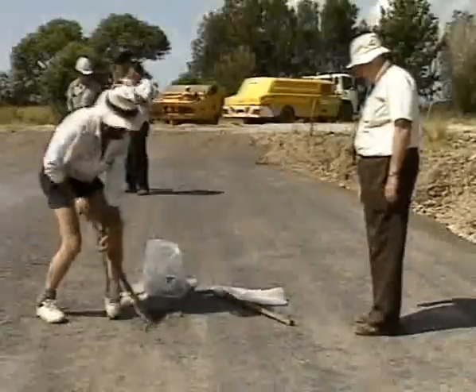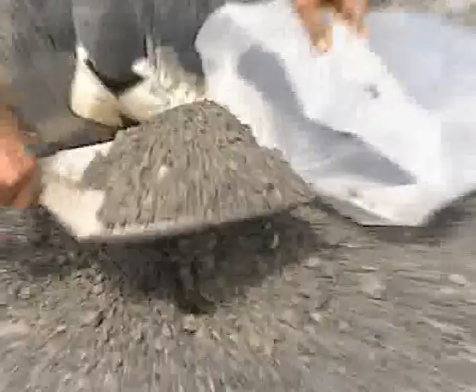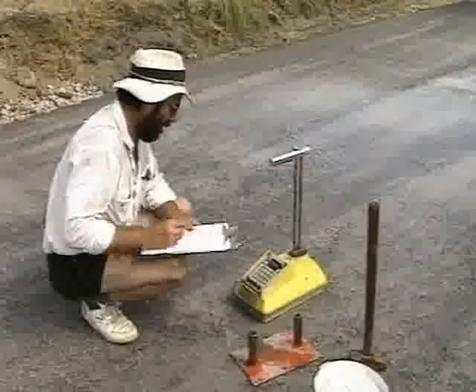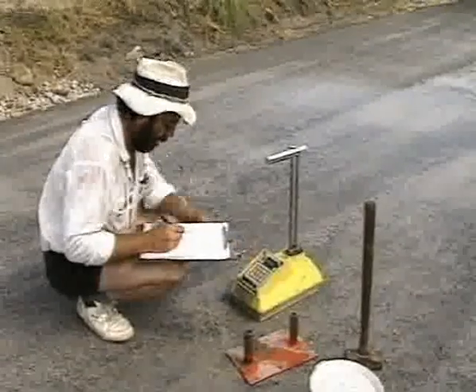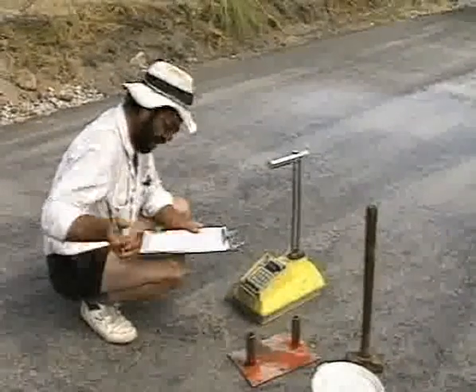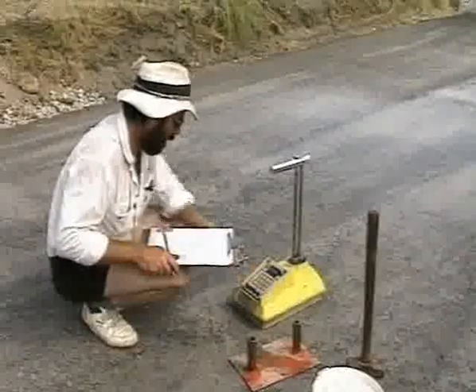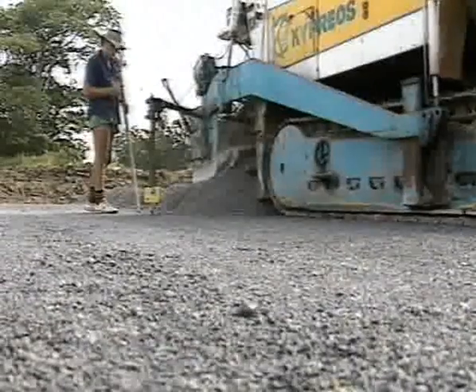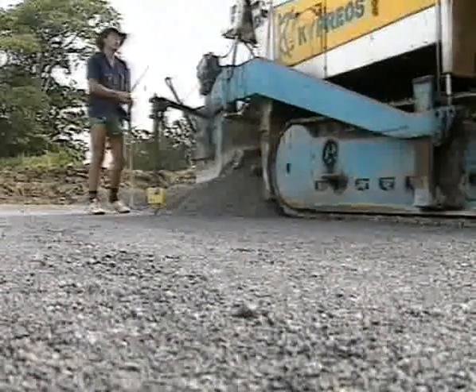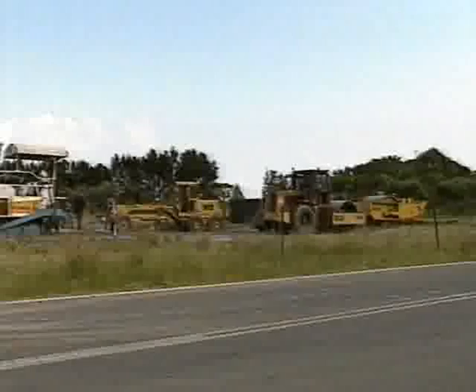For the purpose of the trial, extensive testing was carried out at various stages during the construction. Samples were taken to check if any degradation of the slag occurred. As can be seen, segregation did not take place. The material was also checked for compaction using a nuclear testing device. These tests showed that after initial compaction, the required density had been achieved. Excellent results were also achieved when a similar test was applied to subsequent layers.